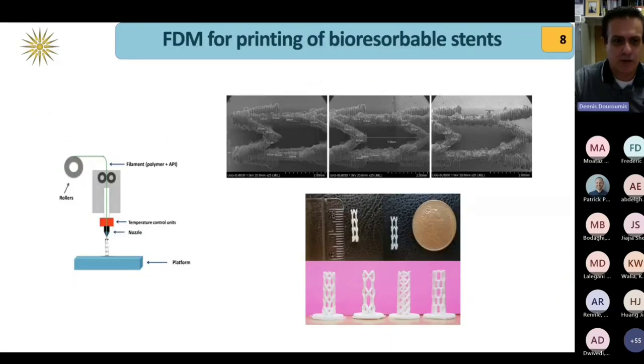However, as you can see here, we had this minor problem or major problem. The surface is not very uniform. You can see the different layers on the surface, and also the other thing was that the thickness of the stent was difficult to take below 300 micrometers, or between 300 and 500. Also, we would have to apply a post-processing technique in order to make the surface smooth, because this can affect the clinical results of the stent.